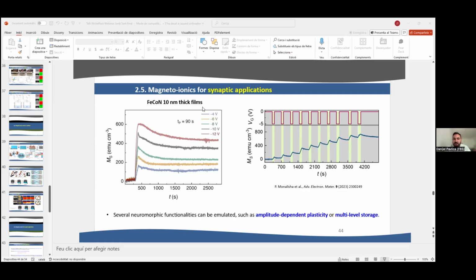In line with what was said previously about new applications, how do you see the future of magnetoionics? What are the most promising directions or applications you foresee for this field? Yeah, I feel that people at the beginning were trying to modulate the magnetic properties of films with magnetoionics for spintronics, for example. But magnetoionics is a bit slow. The fastest in the literature is about microseconds. Compared to spintronics, which is nanoseconds, this is slow. But you can use magnetoionics just for the reconfiguration state, so you can then apply spintronics. If you want to change some property of the film, you apply magnetoionics, you change the properties, and then you can again do your spintronic application. So for reconfiguring the magnetic properties, magnetoionics is good.